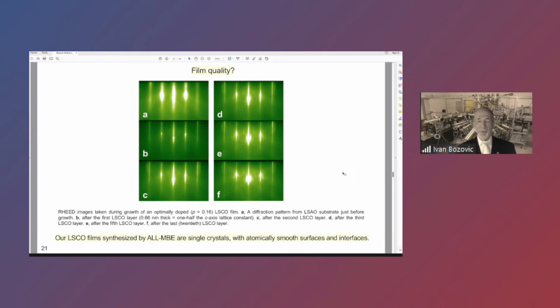What the latter means, since the films are very thin, typically 10, 20 nanometers, is that the film must be pseudomorphic to the substrate, meaning that the lattice constants of the film are the same as those in the substrate. We confirm this by RHEED, but also by highest resolution synchrotron-based X-ray diffraction. If the substrate is tetragonal, so must be the film, and they are, as we verified.